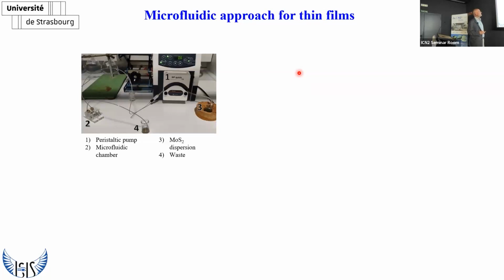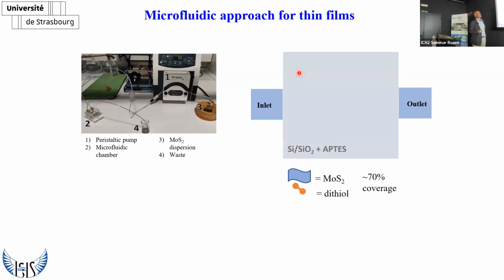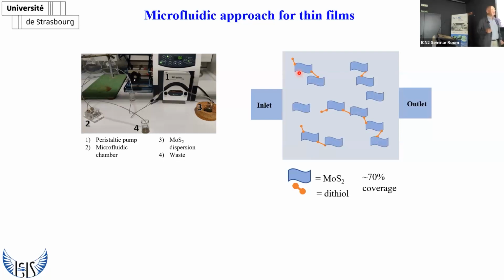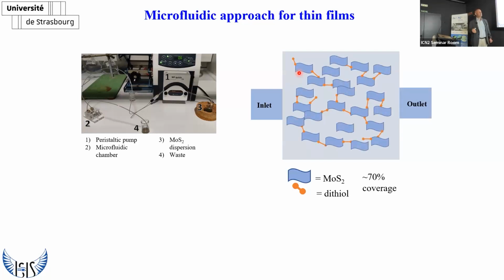The way we have done this was using a microfluidic chamber, because it allows us to have much better control over the formation of this kind of 2D network. Namely, we have an inlet and an outlet, and essentially we can inlet MoS2 or the doubly thiolated molecule, and stepwise you can see that first we put a few flakes, we play with very low concentrations of MoS2, then we decorate with this thiol-related molecule, then we insert again MoS2, and we continue stepwise. Of course, in between each step, there is a washing with the pure solvent.